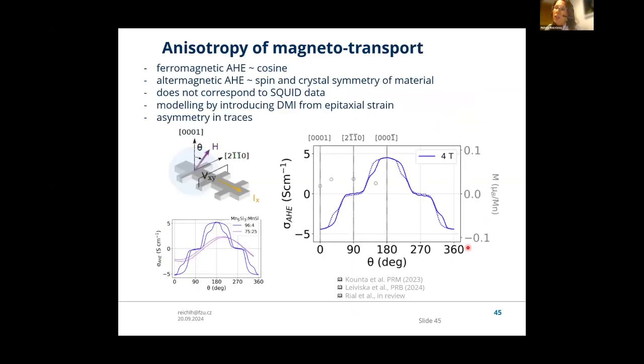And the second thing, which I mentioned already, is that the anomalous Hall effect can be used to detect altermagnetism through the highly anisotropic character of the magnetotransport. In the case of ferromagnets, we typically expect to see some cosine-like behavior, as for standard permalloy or iron or some ferromagnetic material. However, in altermagnets, we know that in certain orientations of the Néel vector, the anomalous Hall effect is simply forbidden. So there should be some plateaus or some regions where the effect is simply not there.